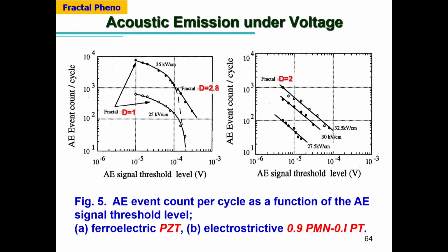That means the acoustic emission energy is higher and higher, and this is lower. So initially, when we look at just the domain reorientation itself, this seems to be a logarithmic decrease. That corresponds to a fractal dimension of one. And the slope for the already saturated part is piezostriction. Therefore, the fractal dimension is 2.8, close to 3.